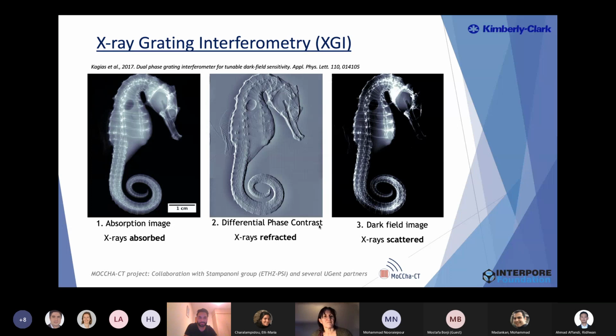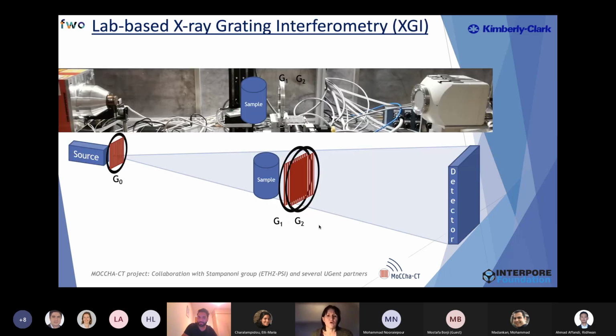The idea is that by applying gratings combined with CT, besides just the normal absorption image, you also get differential phase contrast, and you also get a dark field image. Using this technique, you are able to gain information on sub-resolution features. We have a collaboration with several partners, including Marco Stampanoni from ETH PSI.